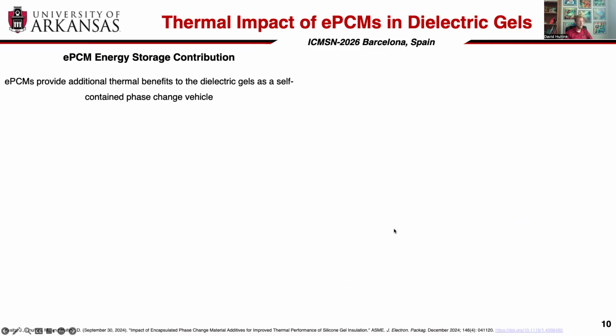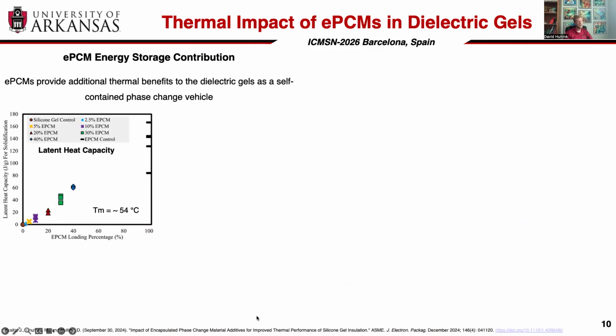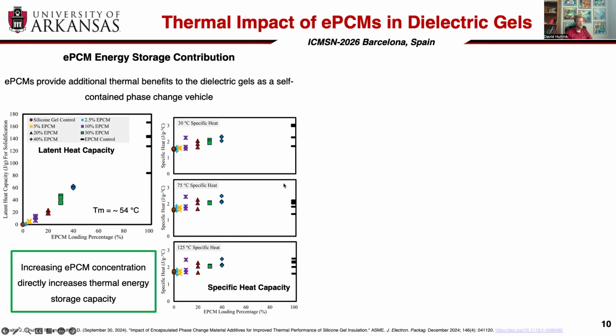So let's take a look at some of the properties that we see thermally when we add these. Of course, the primary metric is, do we add latent heat capacity into the silicone composite that we've created? And the answer, of course, is yes, right? As we add more ePCMs into the system, we see an increase in the total latent heat capacity of the system. We also see a slight increase in the specific heat. So essentially, this also helps with the sensible heat or sensible temperature rise when heat is being generated from the devices. So we see a combined effect of benefit from sensible and latent heat effects.